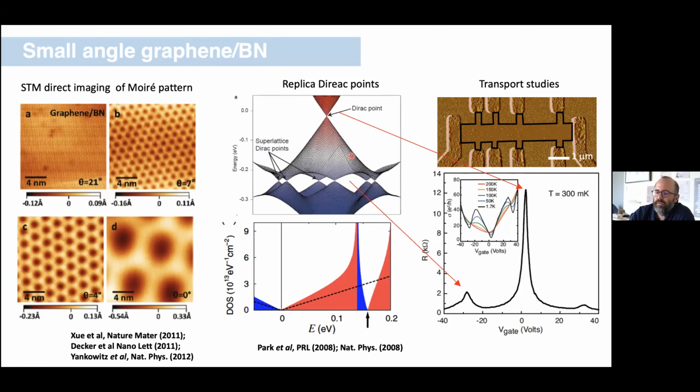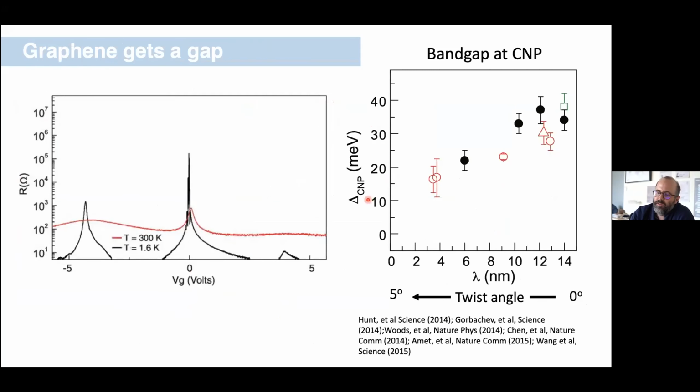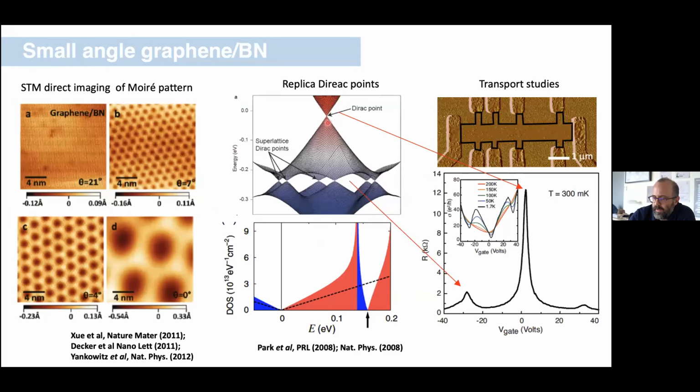And the bulk of the modification is expected to be out here. But when we perform an actual measurement, what we find is that, in fact, coupling between the graphene and the BN opens up a band gap in the system at the charge neutrality point. So we don't retain this closed crossing point. Instead, you can say the system develops a mass term, or a gap opens here.